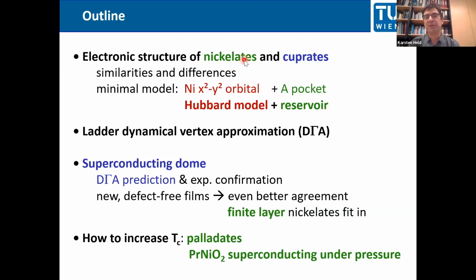From this conventional standard DFT plus DMFT calculation, we arrive at a picture that there's a very correlated x squared minus y squared orbital, but there are additional pockets. So that's different from the cuprates, but these pockets don't hybridize with the x squared minus y squared orbital. So in the first approximation, you can just consider them as a decoupled reservoir. That's the simplest model. There are more complicated ones, as I will point out later. But let's take the simplest model and see how far we come.